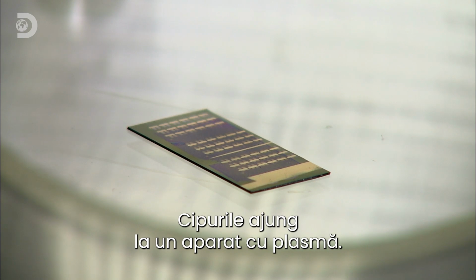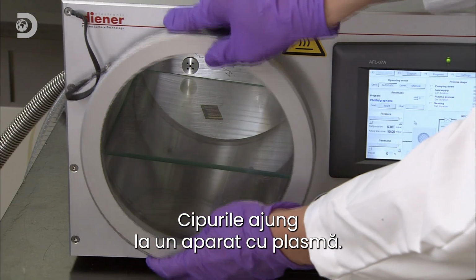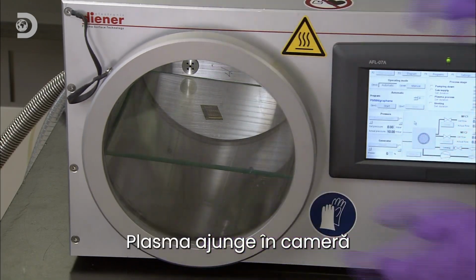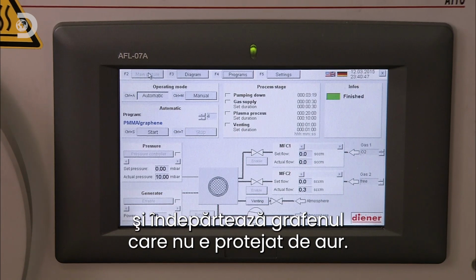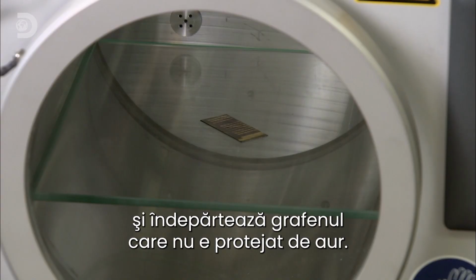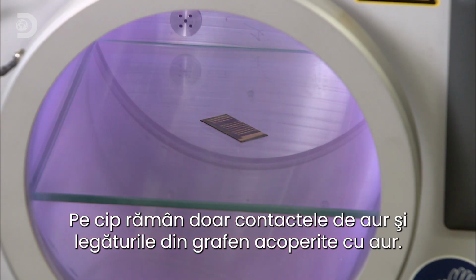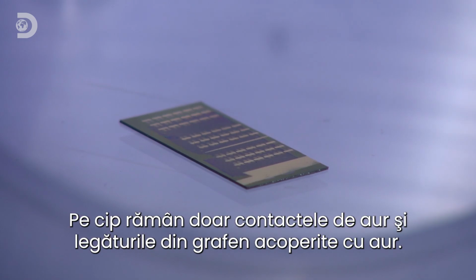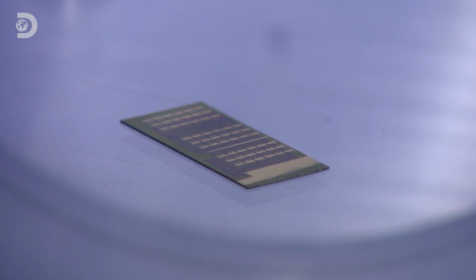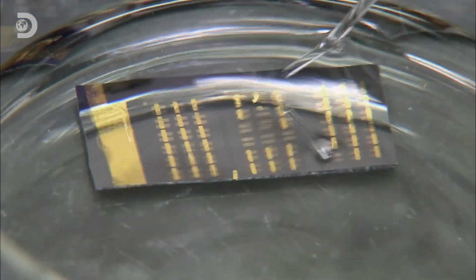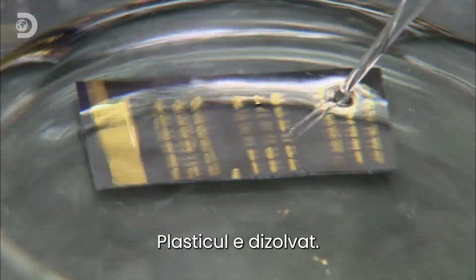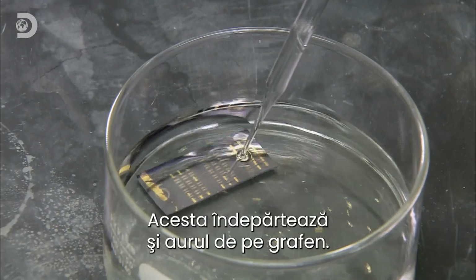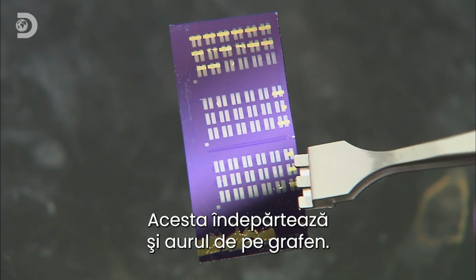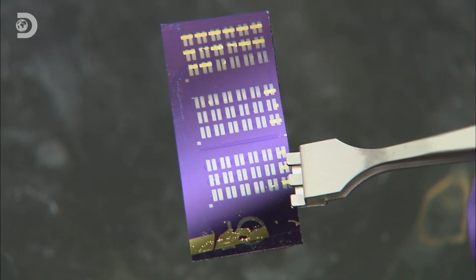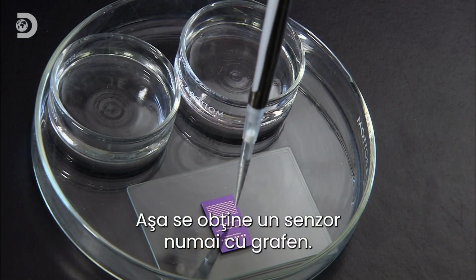The chips are then transferred to a plasma etcher. Plasma gas floods the chamber and strips off all the graphene that isn't protected by gold. Only the gold contacts and the gold-covered graphene runners remain on the chip. Solvent is used to dissolve the plastic backing. It takes the protective gold with it, leaving only the graphene behind. We now have a completed graphene sensor chip.